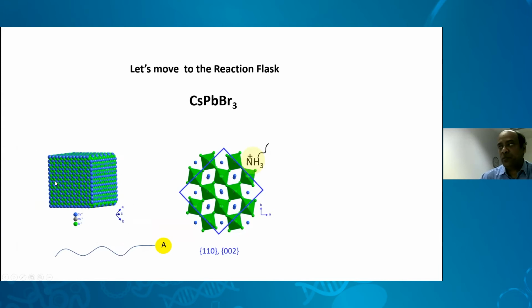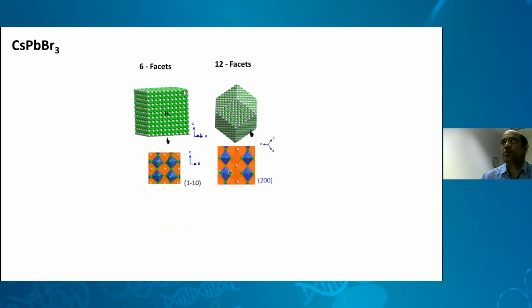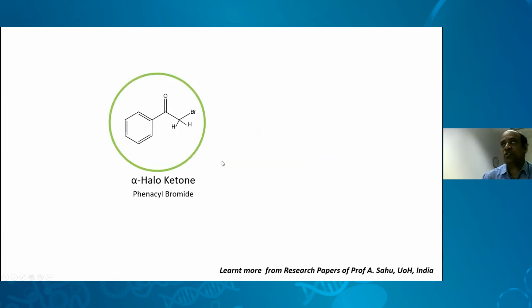So that's what we planned: to get something else, a 12-faceted crystal. Rather than A, we put a B ligand. We have to design something which will not stabilize this type of facets in the 6-faceted cubes, but rather will stabilize these 12-faceted crystals. So we have to go for designing of the B. And that's what we searched in the literature.